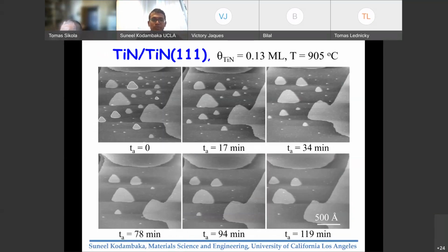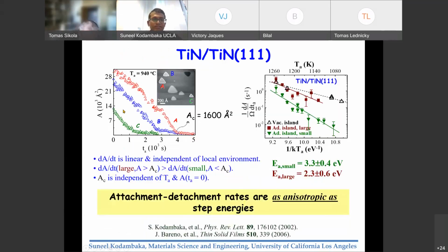We have done similar experiments for titanium nitride on the 111 surface, and here, because the symmetry is different from the 001, you observe these fairly triangular-shaped islands instead of hexagonal shape, and that's because the surface is highly anisotropic. We can extract similar activation energies, and there is some interesting behavior that happens. There is a size-dependent change in the decay behavior, and if you're interested, I can talk to you more about it.